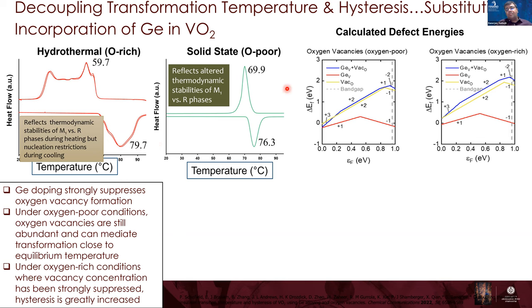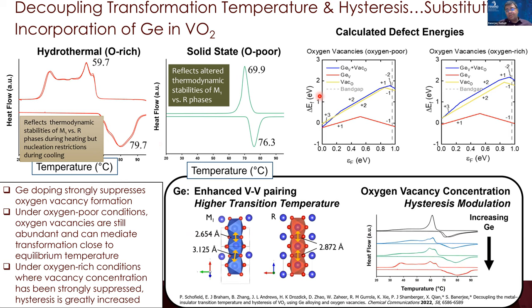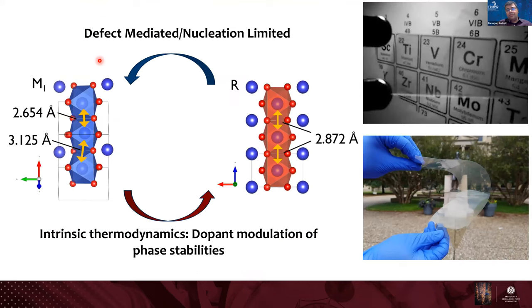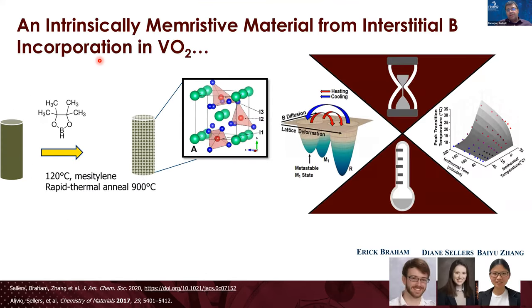Right. So again, germanium suppresses oxygen vacancy concentration. If we are in an oxygen poor environment, we still have sufficient oxygen vacancies, so we can drive the transformation without too much supercooling. If we are under a relatively oxygen rich environment, we have a very, very low concentration of oxygen vacancies, and so we are able to very nicely increase the hysteresis. So that's a nice set of levers, chemical levers, to tune transformation characteristics.